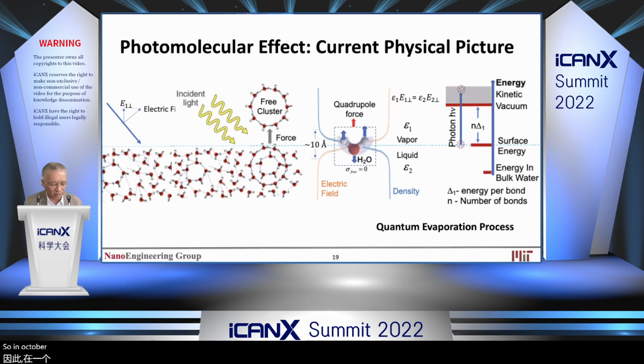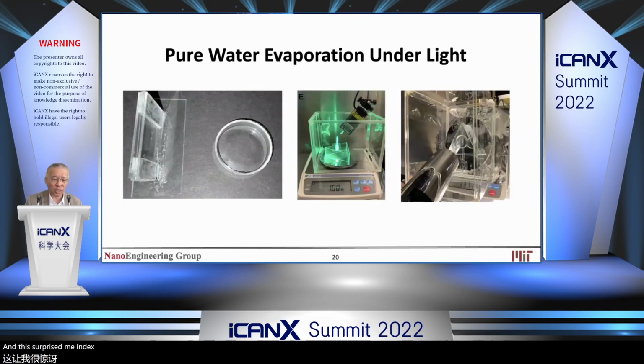So in October last year, I told Jiandong, let's try pure water surface. Maybe we could see something. But I didn't expect to see such a big effect. And this surprised me the most. So we did a pure water experiment under light, LED. So it's very simple, right? And you have a balance in the middle, and you have water in a glass container, and we use LED light emitting, and we also use laser diodes. And this experiment, you need only a few $1,000s to set up.